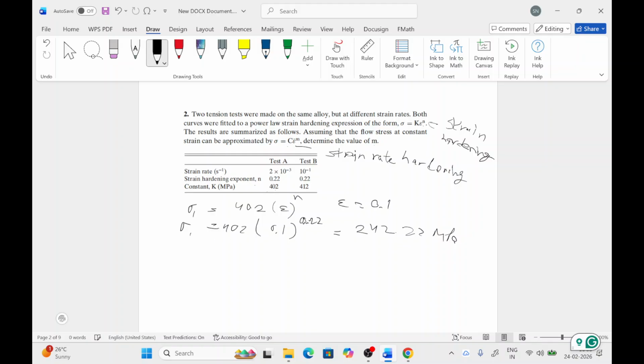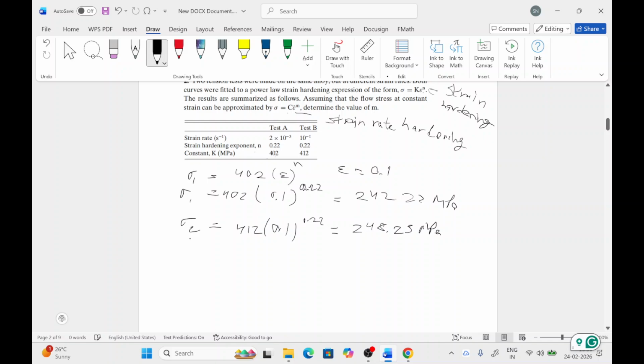And for test B, sigma 2 is 412 times 0.1, and the strain hardening exponent is 0.22. So this will give 248.25. So we know the sigma 1 and sigma 2 values, and the strain rates also we know. We have to find the value of m. So m can be written as ln of sigma 2 by sigma 1 over ln of ε̇2 by ε̇1.